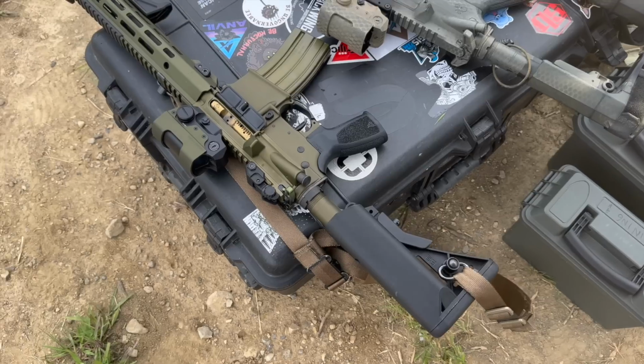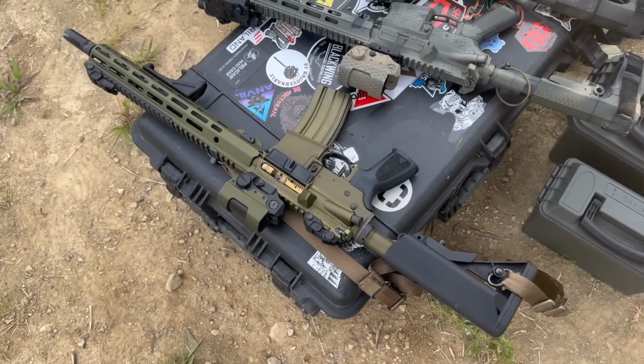We do that because these bolts are machined from bar stock. They are not hammer forged bolts, and so sometimes during the manufacturing process you may have either impurities in the steel or otherwise some structural deformities while that bolt is being machined, and those stressors will come out very early on in the bolt's life. And so when we proof test the bolts, we may shave off a tiny bit of service life towards the tail end of the bolt, but we effectively remove all of the bolts that will be breaking early within 500 rounds, as a result of poor metallurgy or heat treat or something like that. And it helps us with a little bit of quality control.